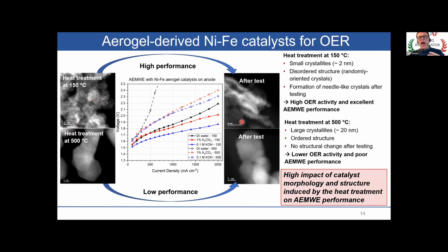So when we test and apply the high potential of the anode of the electrolyzer, this disordered structure of randomly oriented small crystals has the ability to modify and create this lamellar structure, which we attribute to be iron doped nickel oxyhydroxide, which is the highly active phase for oxygen evolution reaction. On the other hand, these larger crystals of the commercial materials or catalysts heat treated at high temperature do not have that ability. They stay in the same form, and so they have a certain oxygen evolution reaction activity, but not that high, and they cannot take advantage of the random iron doping into the original nickel hydroxide structure.